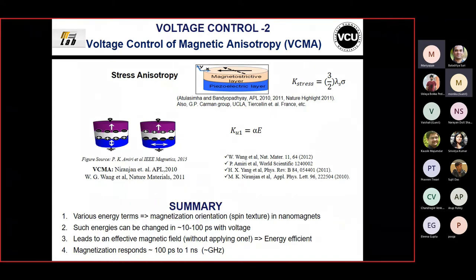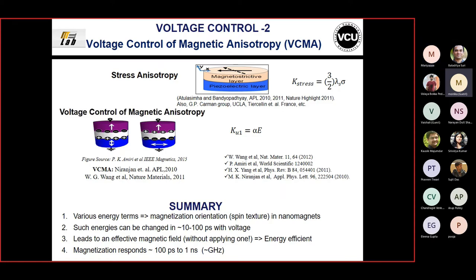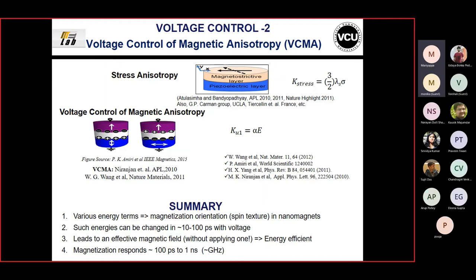Similarly with VCMA, you apply an electric field that directly affects the anisotropy - effectively applying an effective magnetic field that rotates or reorients your magnetization, in this case from out of plane. These various energy terms control the spin texture in nanoscale magnets. Such energies can be changed purely with voltage and the response can be in 10 to 100s of picoseconds, leading to an effective magnetic field without really applying one. The field magnitude is moderate, but good enough that with a damped rotation or precession, you can get switching in 100 picoseconds to one nanosecond.